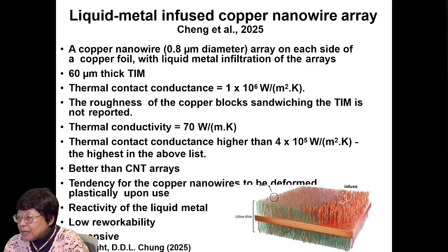This material is better than the CNT arrays in the performance. However, there's tendency for the copper nanowires to be deformed plastically upon use. And the reactivity of the liquid metal is of concern, and also low reworkability, and it's also expensive.